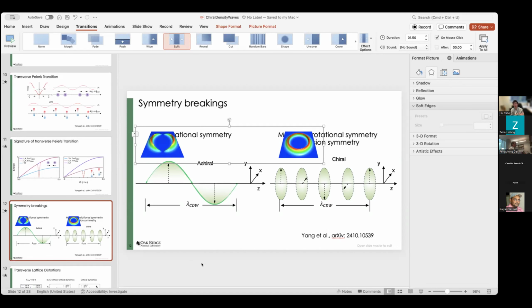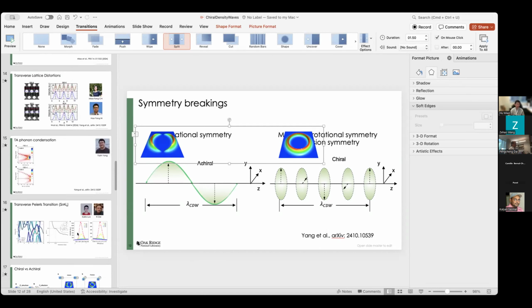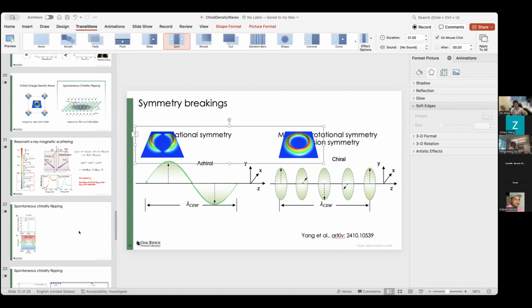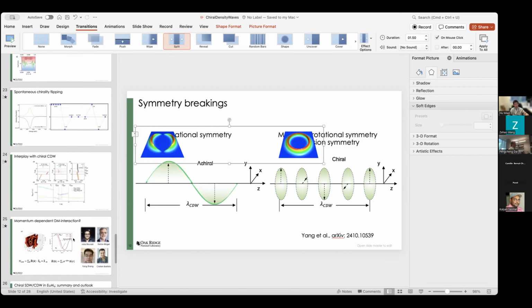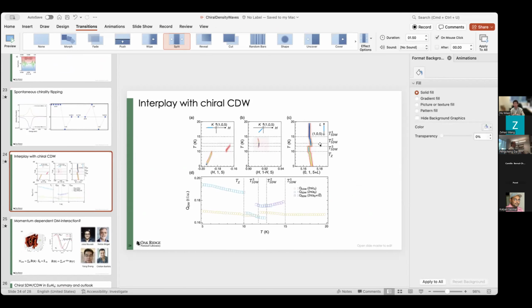I thought there's a strong coupling. I mean, I saw in the later talk you said there's also a coupling with the spin. Yeah, that's right. That's true. Once we went to lower temperature, when the magnetic phase pops up, they become strongly coupled. And exactly how they are coupled, we don't know yet. But based on the data, we know it must be a very strong coupling. I see. So the chiral CDW order occurs at 140 K, at higher temperature, and then it only couples to spin at lower temperature. Yes, I think because the spin can only order at a lower temperature. It's a rare earth, so it's not surprising.